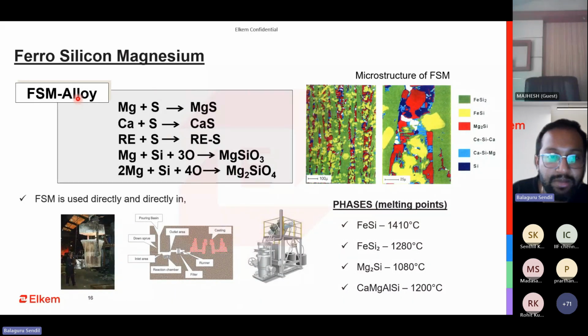If you're using ferrosilicon magnesium, these are all the positive reactions that will happen, which will help in your nodularizing effect. When you have all these reactions happening, you do not need so much magnesium. Your recovery always improves. In pure magnesium, you get about 30 to 40% recovery. With FSM, you can expect somewhere between 60 to 80% magnesium recovery. And in in-mold FSM, more than 85 to 90% magnesium recovery is possible.